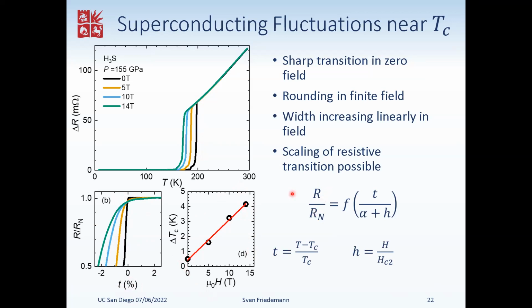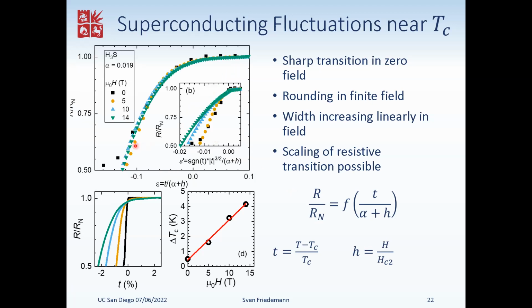Now, it is expected that the transition width is a function of the magnetic field. Specifically, it is expected that it should be a function of temperature to the power of 3/2 over field, but actually we do see it linear. Indeed, if we attempt to scale the resistance, so this is the resistance of all these curves plotted versus reduced temperature divided by reduced field plus a constant, where this constant essentially reflects the finite width in zero field, or this intercept down here, you can see that the data collapse over a large range, namely down to half the transition. If we were to try the same with temperature to the 3/2, there's certainly a much worse collapse. There's no collapse of the data.